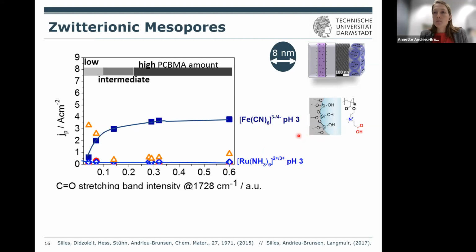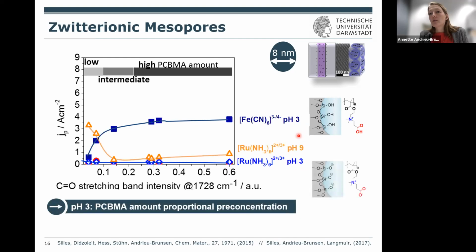So now the interesting point is what happens if you change to the zwitterionic state. What you would imagine very intuitively is that now, okay, that's neutral, right? You have a positive charge, you have a negative charge. It should be somehow similar to the example with the phosphate group with a calcium ion. This neutralizes and the pores open. But this is actually not what you see.